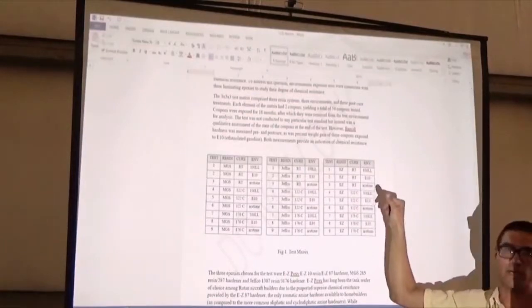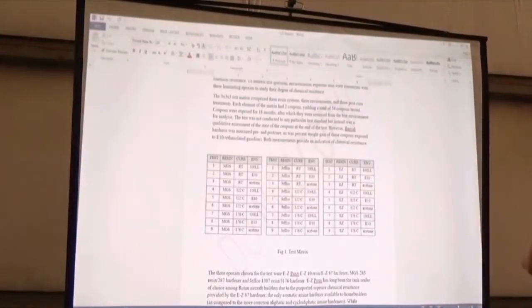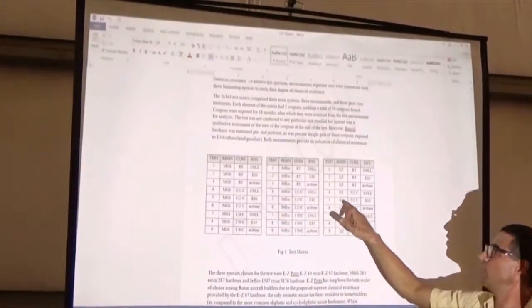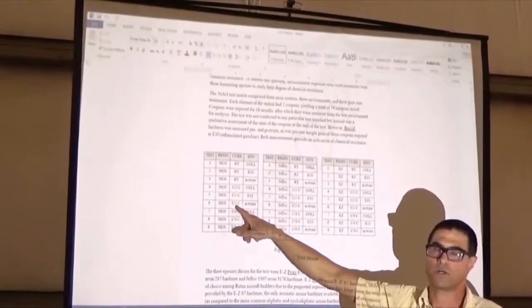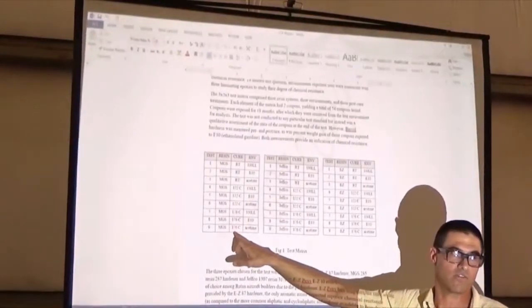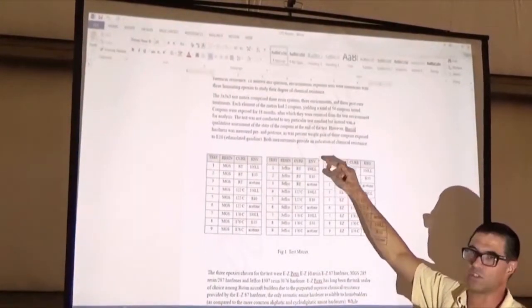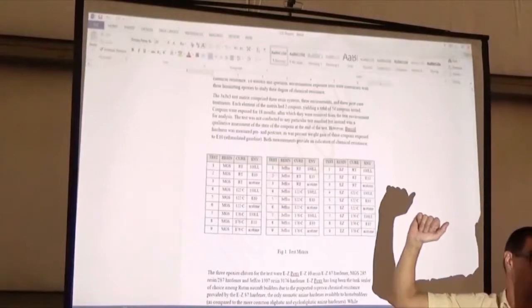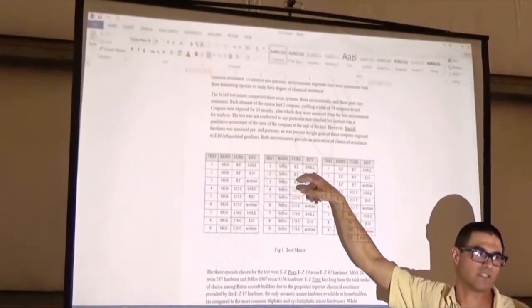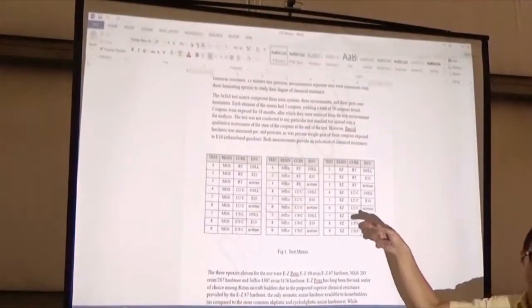So I had a matrix of resins, chemicals, and post-cures. I looked at MGS resin, Jeffco, and Easy epoxy. I looked at room temperature cure, a 122 degree Fahrenheit cure (this should say F, not C), and 176 degree Fahrenheit cure. And then I exposed it to avgas, ethanol-blended motor gas, and then acetone. The reason I did the acetone was because I assumed that these would probably not have any appreciable effect over the 18 months of the test. But the acetone was a way of speeding things up, kind of doing an acid test, as it were.